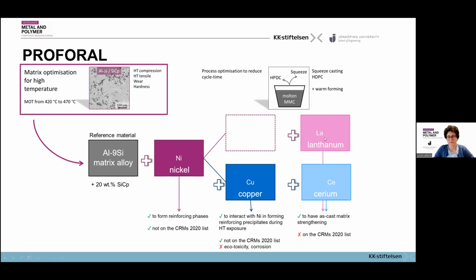And then we also decided to look at the role of lanthanum and cerium, so rare earth elements in this case, which in literature are said to have as-cast matrix strengthening, but the negative side is that they are on the critical raw material list. So that would be a challenge for sourcing in this case of these two elements.